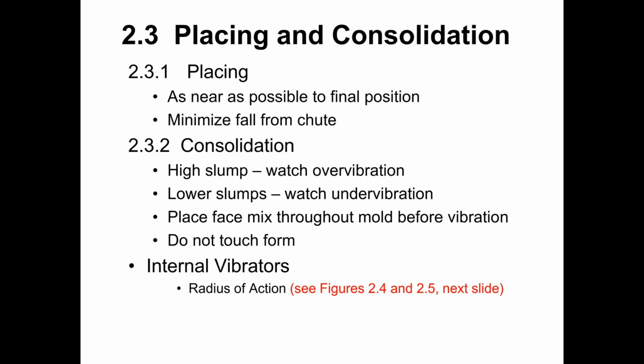So for each drop of the internal vibrator, the radius of action should overlap. We want to avoid turning the internal vibrator on and off while it is in the concrete. That can cause void space within the concrete, so the internal vibrator should always be running when it's inserted into the concrete and remain running until it is removed from the concrete.